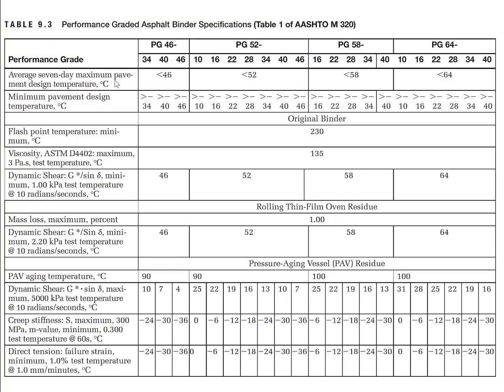The first row is the design maximum temperature and the second row is the design minimum temperature for each grade. For the original, unaged binder, three tests are performed: the flashpoint test, the rotational viscometer test, and the dynamic shear rheometer test. The flashpoint test measures the flashpoint temperature, which should be a minimum of 230 degrees Celsius. The rotational viscometer test measures viscosity at 135 degrees Celsius, which is exactly 275 degrees Fahrenheit, and the measured viscosity should be smaller than the specified maximum value.